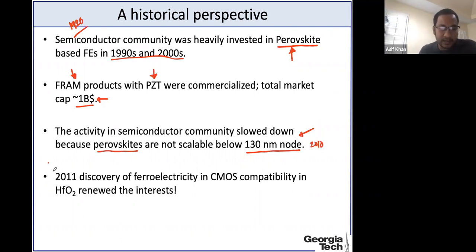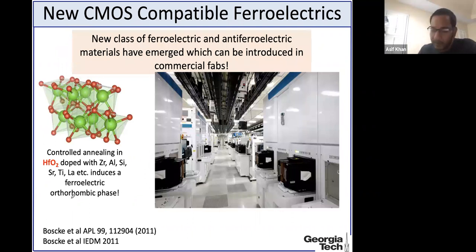But again, as always, a surprise came in 2011, when ferroelectricity was discovered in hafnia. So what is hafnia? If you have a state-of-the-art electronic gadget, for example a phone or a laptop or computer, all of the transistors actually have hafnia as the gate dielectric. What the German group in 2011 reported was that if you take the same hafnia or an alloyed variant of this material and anneal it under certain conditions, this material becomes ferroelectric and also can become a sister phenomenon of ferroelectricity, antiferroelectric.